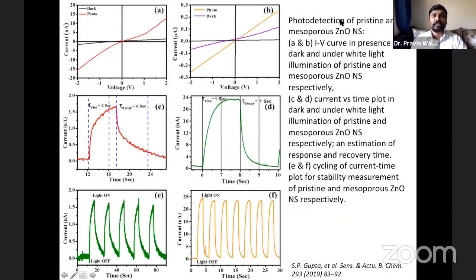So here, let's have a look at the photodetector properties of the zinc oxide, right? So these two are different things here. This is the pristine zinc oxide, and this is mesoporous zinc oxide. And you see here in the dark and in photo, the photocurrent generated in this pristine zinc oxide structure and in the mesoporous zinc oxide structure. So we have observed that performance in the mesoporous zinc oxide structure is quite good, right? And here you see this is just a current versus time plot, right? And you can find the response time is 4 seconds and recovery time is 6 seconds, right? So here the response has been sped up, so it speeds up the process of photodetection in the case of mesoporous, which has oxygen deficiencies as compared to this one.